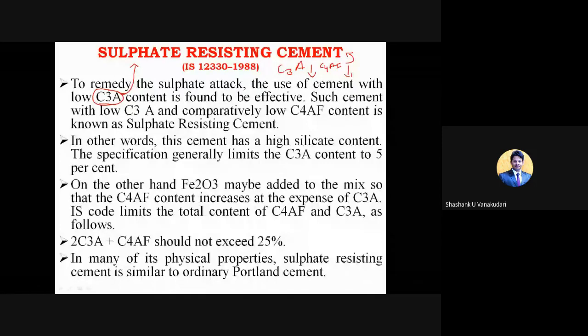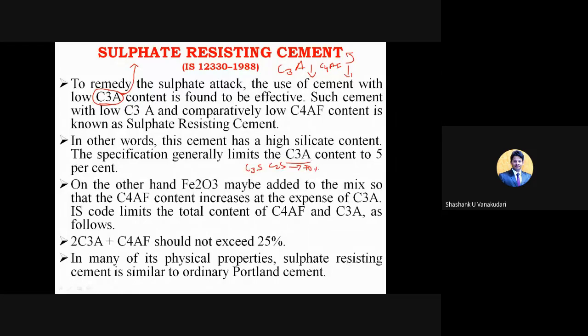And in other words, this cement has a high silicate content, and the specifications generally limit the C3A content to 5%. So C3S and C2S together form 70%, right? And the remaining 30% is with the C3A as well as C4AF. But now the C3A has to be restricted only to